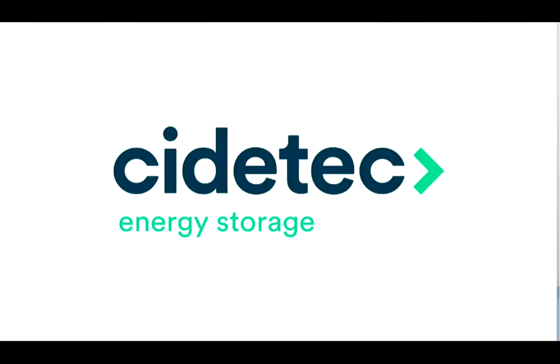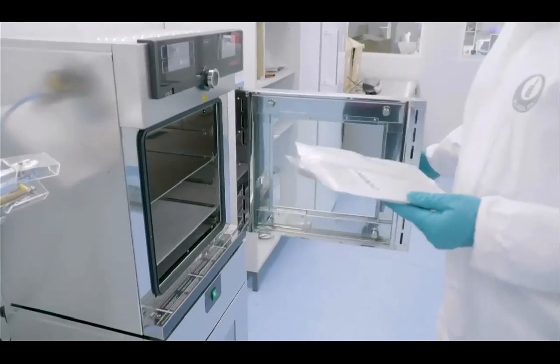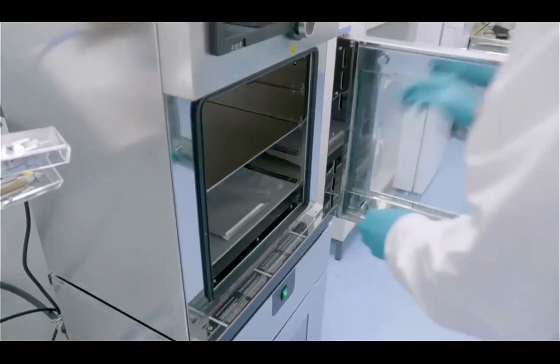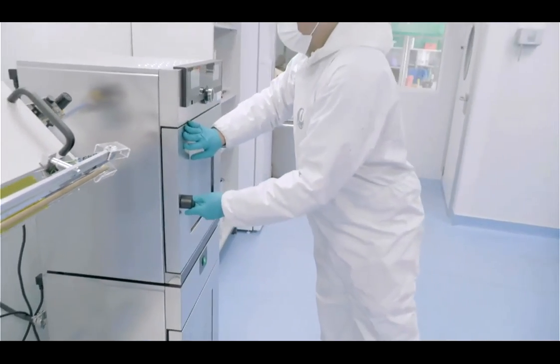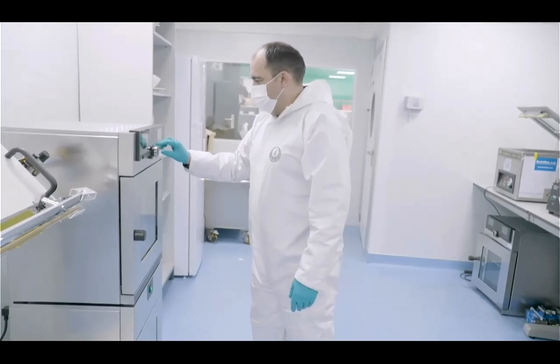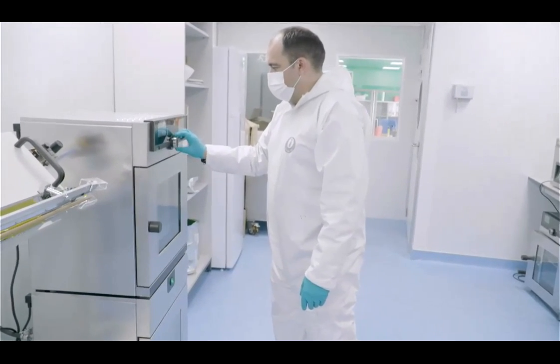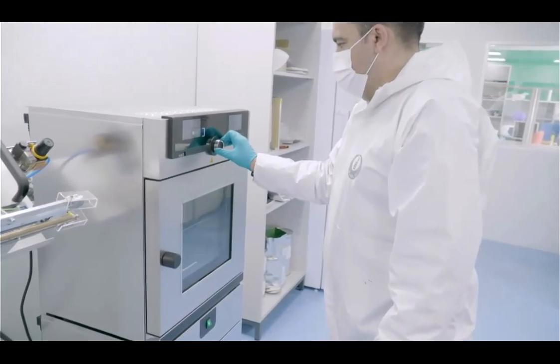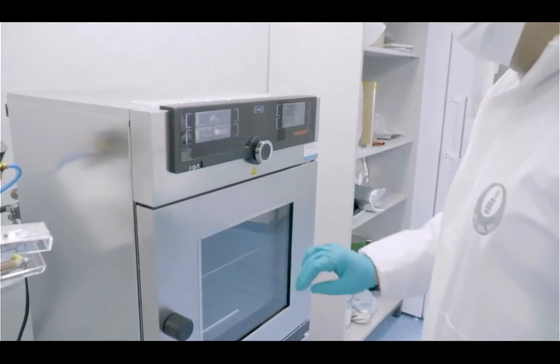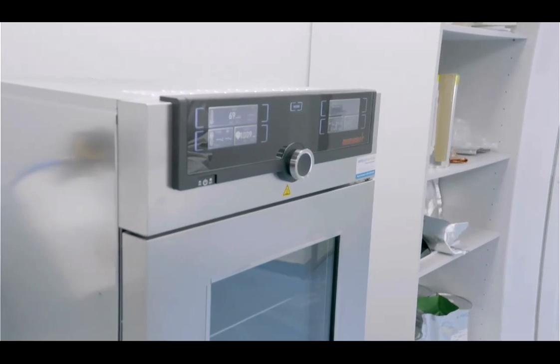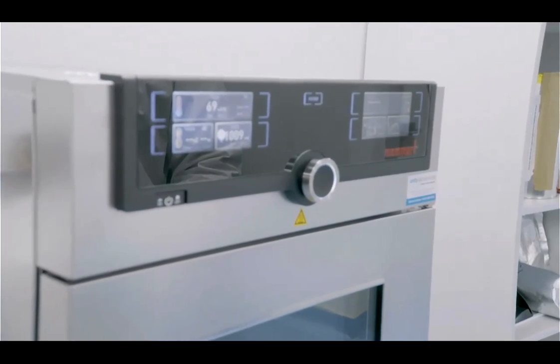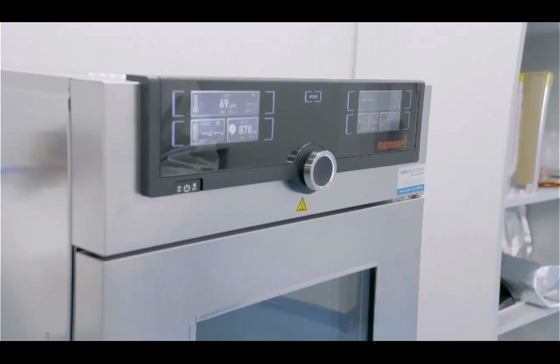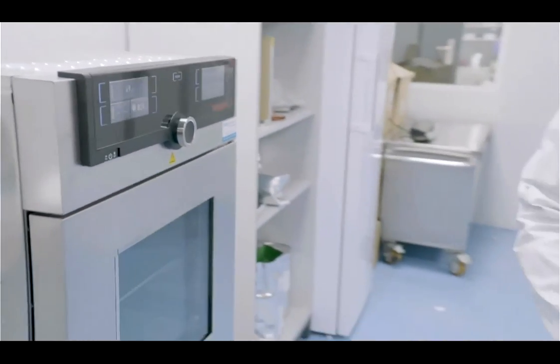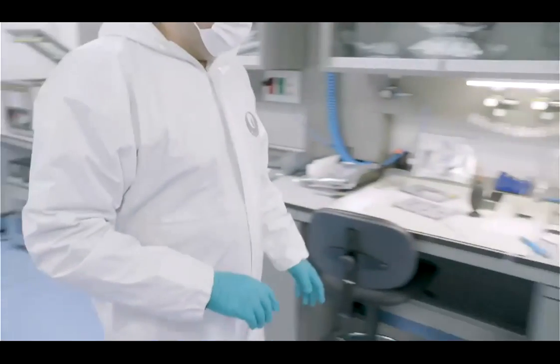Okay, so the drying, it is a very, very important step, because as you have seen, all the processes are done at ambient conditions. So the stacks are dried in the vacuum oven inside the dry room. The drying time is approximately between 12 hours and 24 hours. It will depend on the electrode. And during this drying process, we will remove all the residual moisture of the electrode. The drying conditions are optimized using the Karl Fischer.